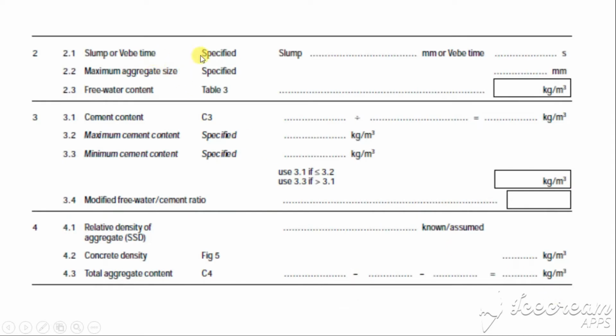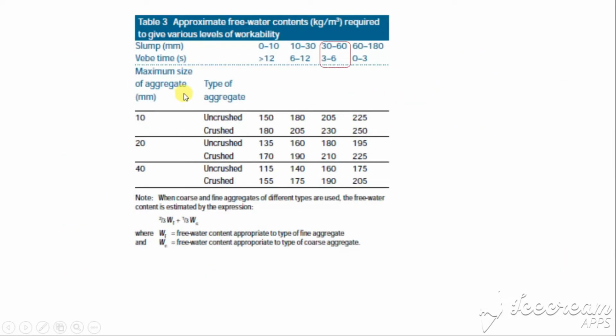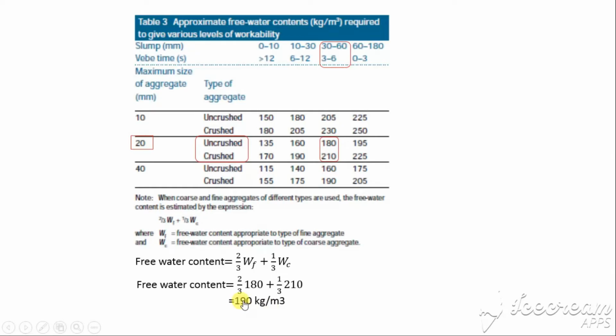For the next step, choose the slump value 30 to 60 and the maximum aggregate size we use 20 mm, and for the free water content, we will refer to table 3. We get 190 here. How do we get the free water content? This slump 30 to 60, our maximum aggregate is 20, and the type of aggregate is crushed and uncrushed. If we use a different type of aggregate, we need to calculate using this formula. We get 190 kgs per meter cube for the free water content.